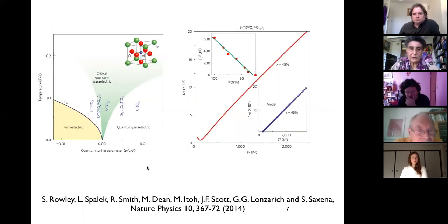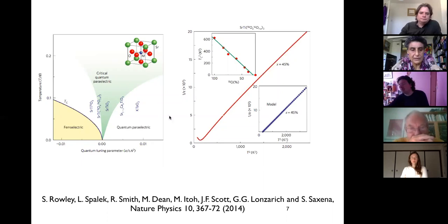Now, last time we talked about strontium titanate, the isovalent cousin of barium titanate. It is stubborn. It doesn't want to be ferroelectric, but it can be nudged. And in fact, we talked about the fact that if you take strontium titanate and substitute oxygen 18 for oxygen 16, you can drive it ferroelectric. Here we have Tc squared versus oxygen 18 concentration. And the Cambridge group, led by Stephen Rowley, has shown that strontium titanate is just to the right of the quantum critical point, and you can do an oxygen 18 substitution and drive it closer to the quantum critical point. This is actually a little bit to the left. Okay, so